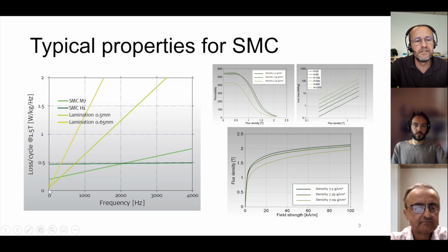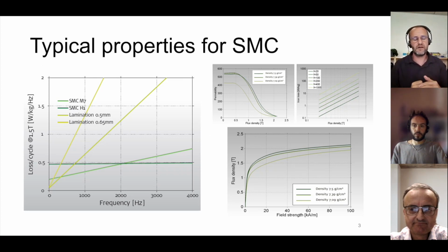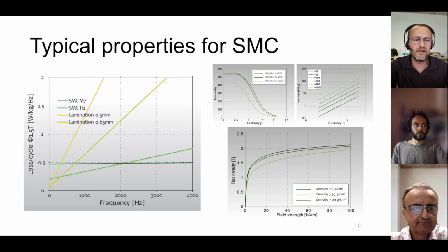And if we look at the DC level where we have no frequency, typical SMC has a higher loss because the heat treatment that we make after compaction does not fully anneal. So we still have some deformation hardening left over in the part. If we went to fully annealing, we would also initiate a sintering, and a sintering would shortcut the particles and destroy the isolation. So therefore, we have in SMC a trade-off. How high can you go in temperature to have a better annealing, but not too high to destroy the isolation layer. So therefore, we typically see a higher loss at low frequency compared to other materials.